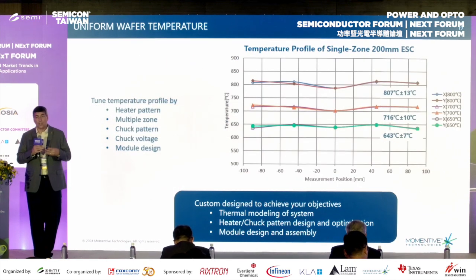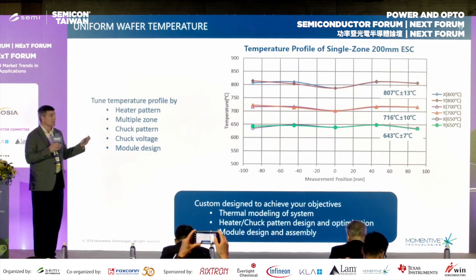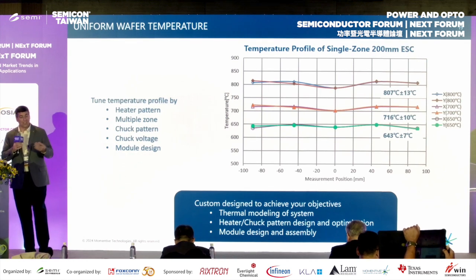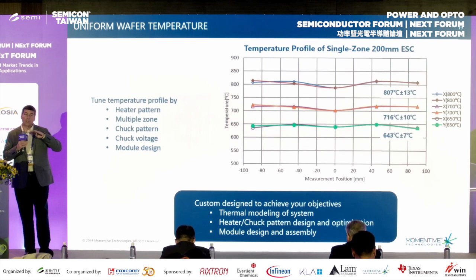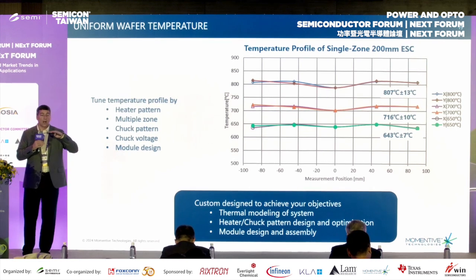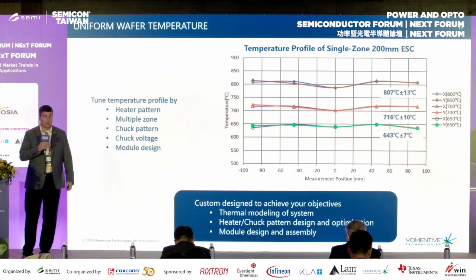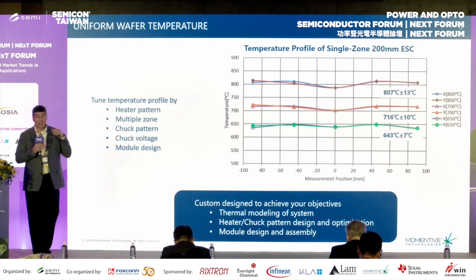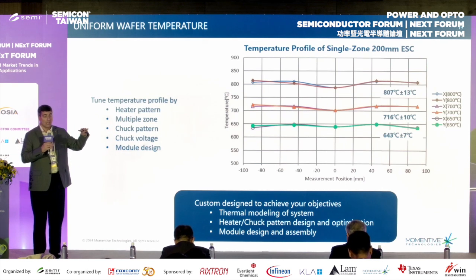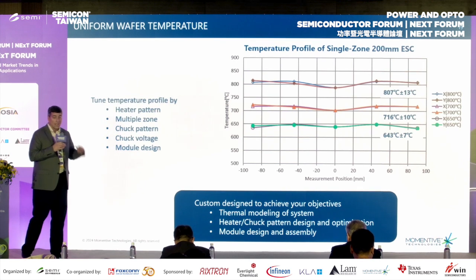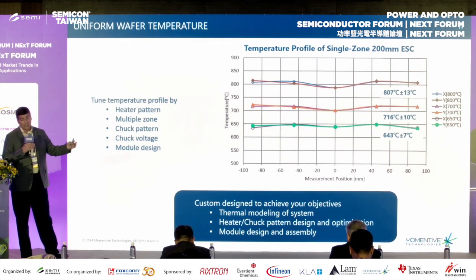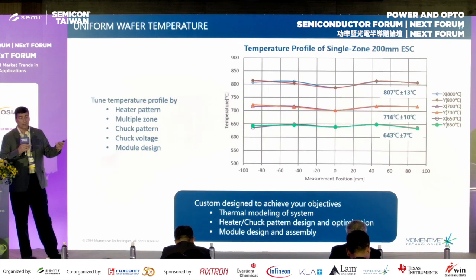Again, obviously we're not going to run this at 23 degrees a second for a standard tool, it's more just an example, but because of the high thermal conductivity within the material, it allows us to get fairly flat temperature profiles. So again, this is a single zone electrostatic chuck heater at 640 degrees, 700, and 800 degrees Celsius, and you see we're holding about 7 to 13 degrees C flat. Right? Not bad considering that's a single zone.